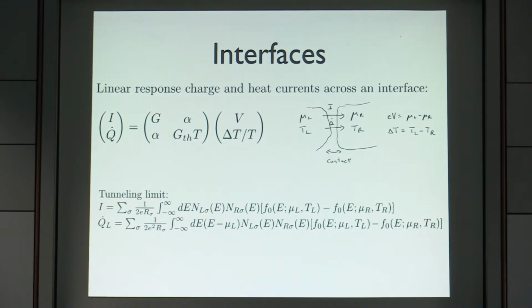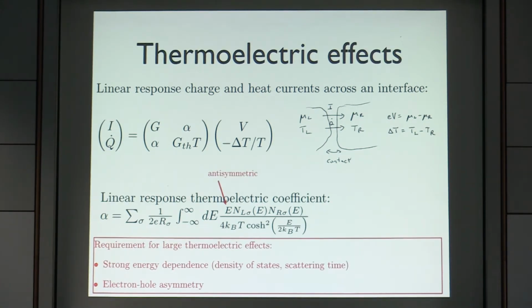So I proceed a bit. Instead of the Boltzmann model, I can make a tunneling model for my currents. I basically get the same results. In this case, alpha is given by the densities of states on both sides of the barrier. So the requirement for large thermoelectric effects is strong energy dependence and electron-hole asymmetry, which basically means this odd component in the energy.